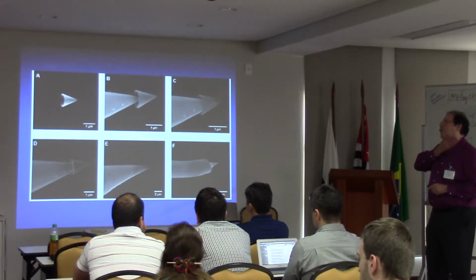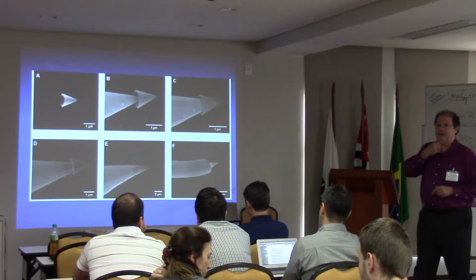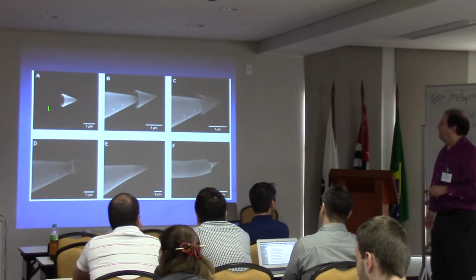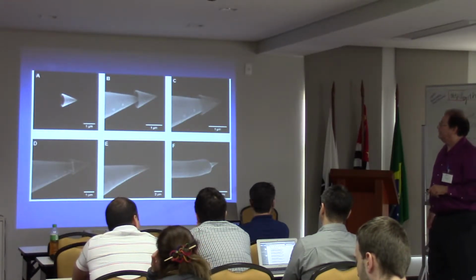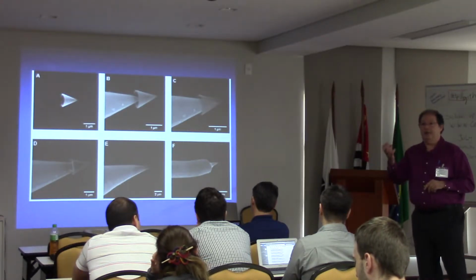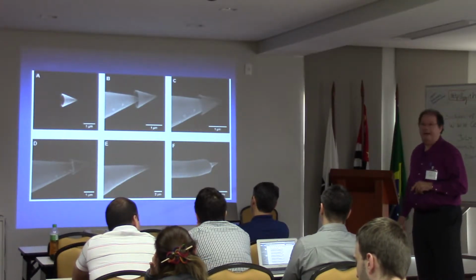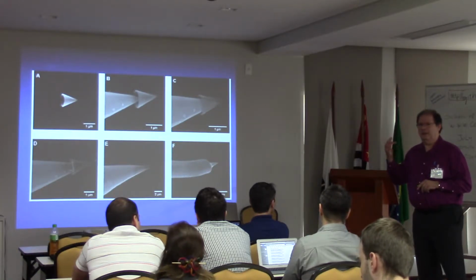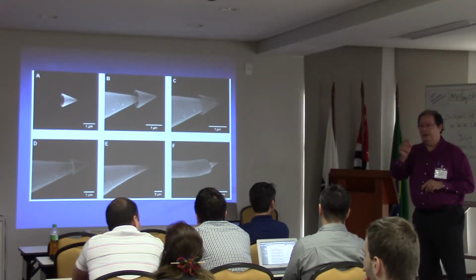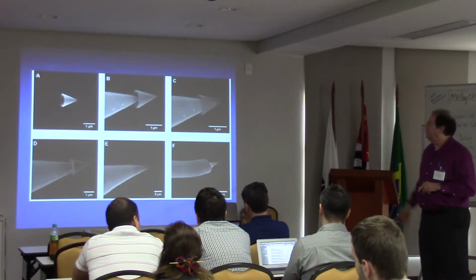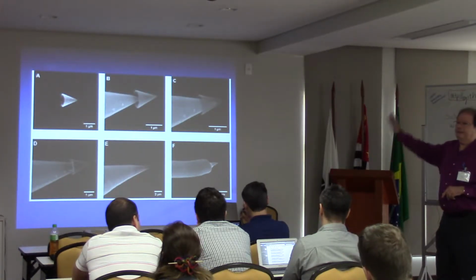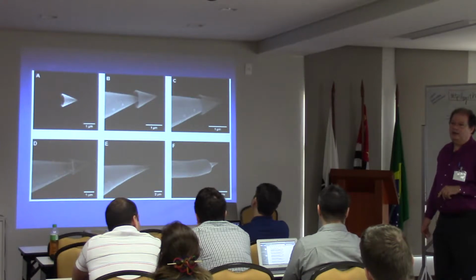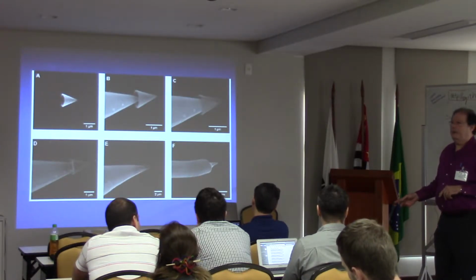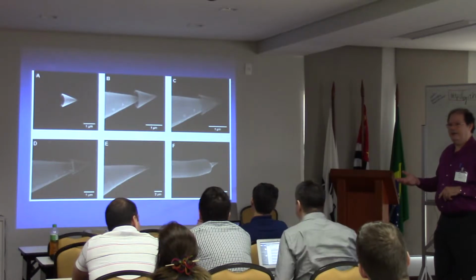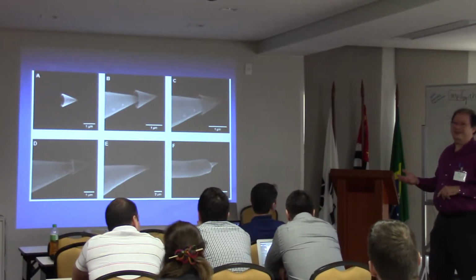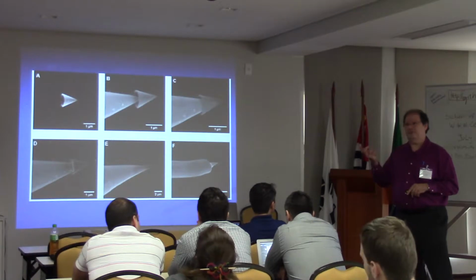So they are trying to solve how to make better tips. They come with this idea to encapsulate the gold tips with carbon nanocones. This is a commercial structure you can buy. There are only 3 companies selling this, but you can do this. It's an almost micro-scale nanocone. So they encapsulate it, and then the tip lasts longer and produces better images. But they want to see why that is, because the tip becomes much better than they guessed it would from just the encapsulation.